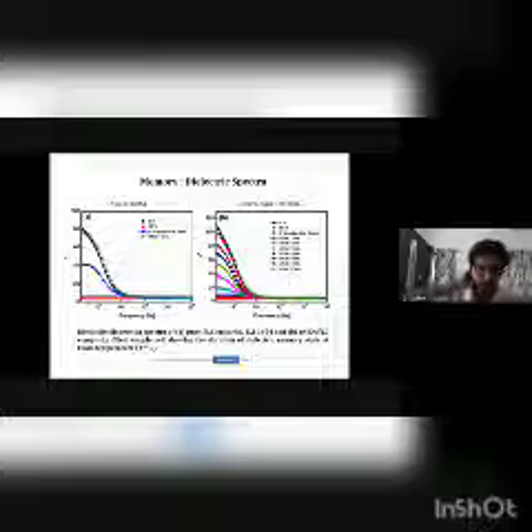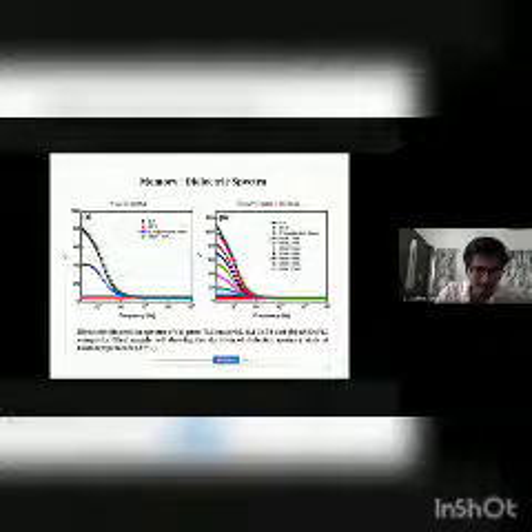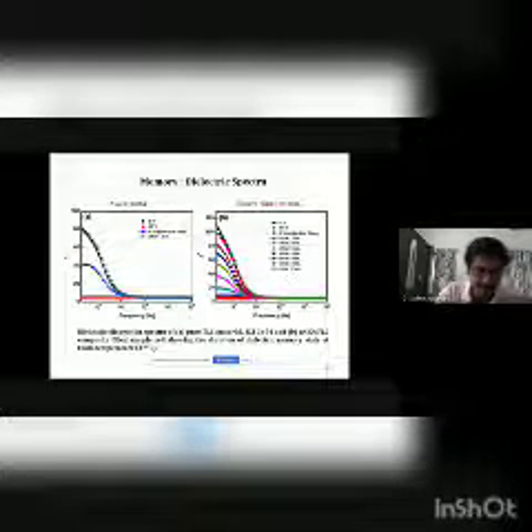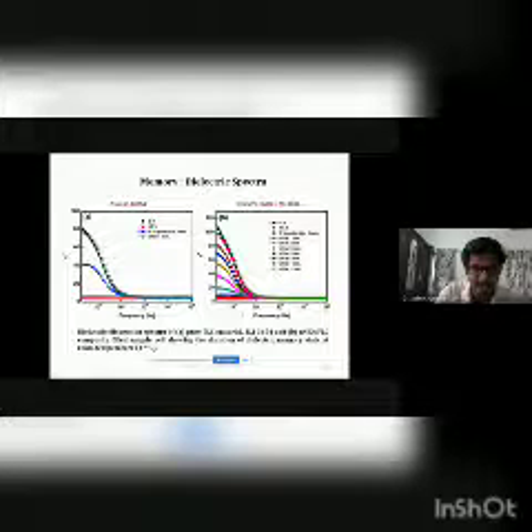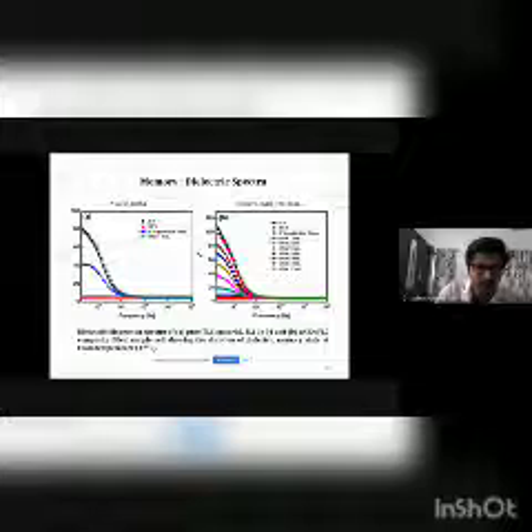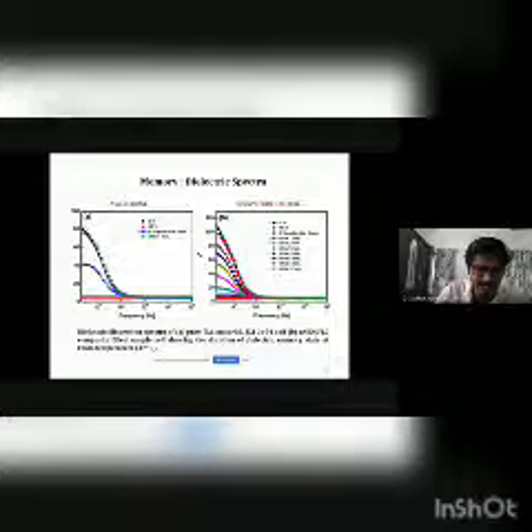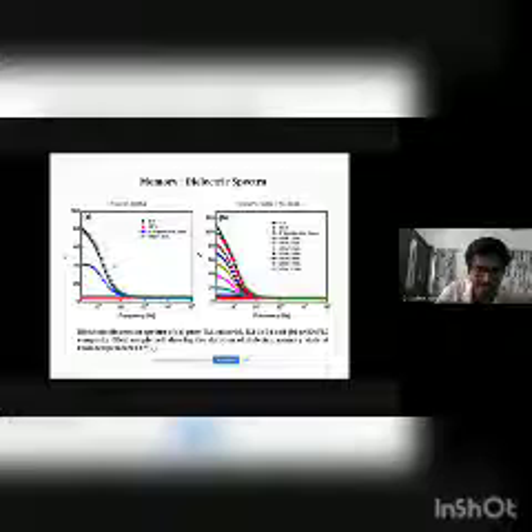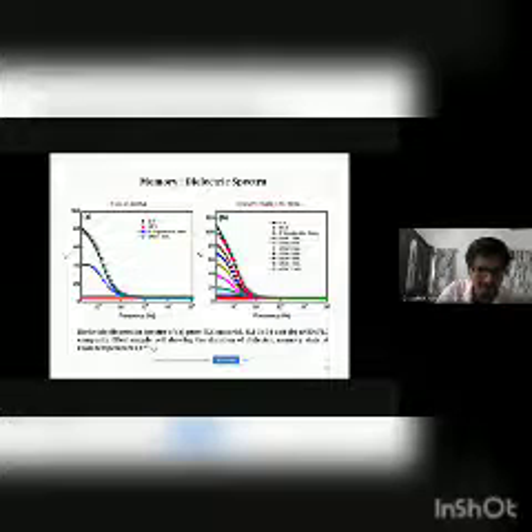Here in dielectric spectroscopy, you can see the variation of dielectric permittivity with various frequencies for the pure material and for the composite material. When you are applying 0 volt, meaning there is no external DC bias, your dielectric response is like this. The real part of permittivity is varying like this.